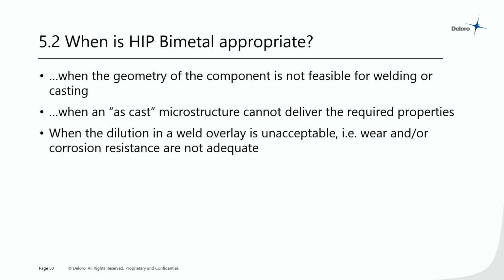And when is bimetal HIP appropriate? When the geometry is not feasible for welding or casting. That would be the first clear application. If you can't apply a weld hard facing, you can't make a casting, then HIP bimetal is obviously the way to go. Or when the properties from an as-cast or an as-welded microstructure are simply not adequate. Or when dilution from a weld overlay is unacceptable.